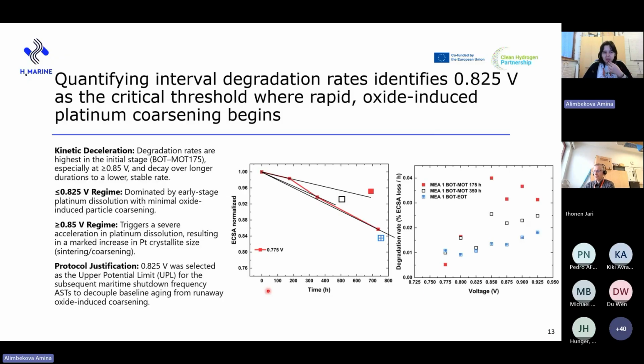These kinetic insights give us a justification for using 825 millivolts as the upper potential limit for our subsequent shutdown protocol. By placing our limit at this voltage value, we ensure that our baseline degradation is slow, so we can isolate the impact of the actual transients themselves without inducing more degradation from the high voltage holds.